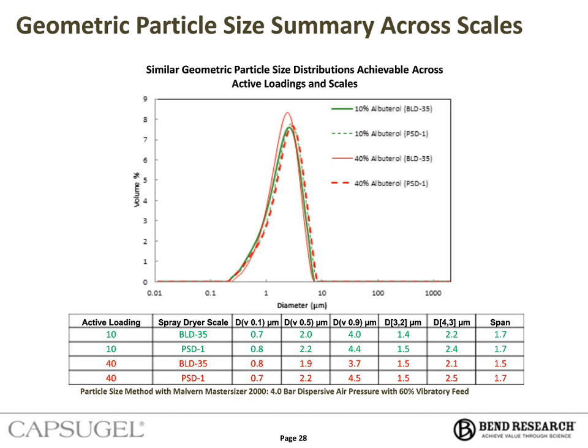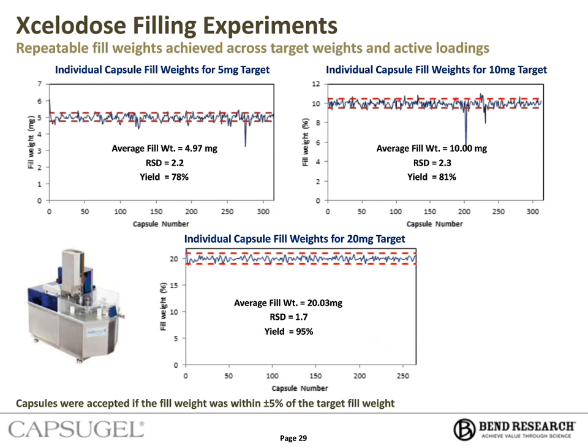And so moving on to a filling process that's more scalable than hand-filled capsules, we show the Xcelodose filling results. So here we took the 10% active loading formulations and filled them at 5, 10, and 20 milligram target fill weights. And again, this was done to show, coupled with the different active loadings, the wide dose ranges that can be achievable with this process. So again, in each of the target fill weights, we have an average fill weight very close to the target. We have RSDs less than 3%, and high yields seen across each of the target fill weights.